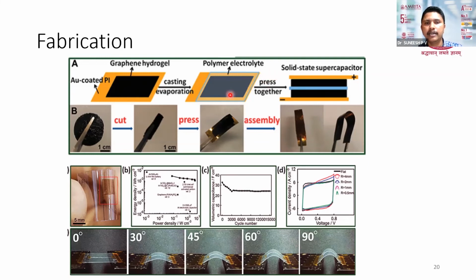Then keep another plate of this graphene hydrogel on the top, and then you can press it, and you can see one electrode here, another electrode here, and in between that the sandwiched electrolyte, and that will act as a supercapacitor. Because of the high surface area of graphene hydrogel, it can store a very high amount of charge, and it can be made into a flexible form. You can see here they are bending the supercapacitor, and the efficiency is not affected upon those bending cycles.